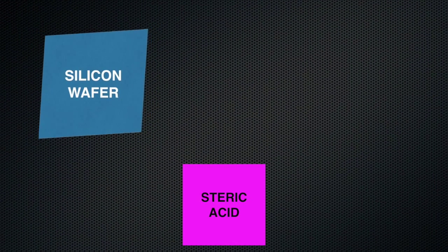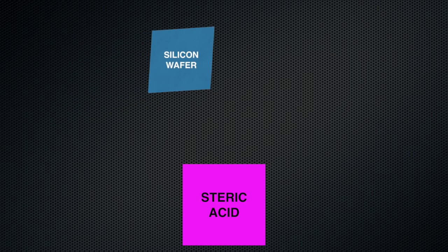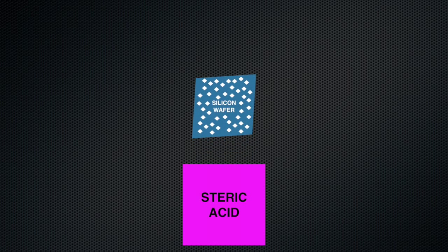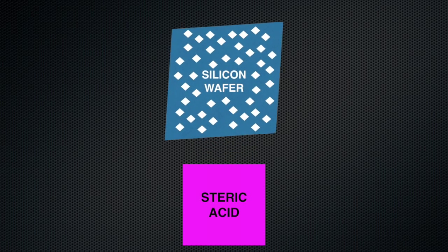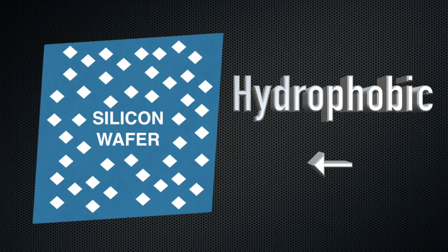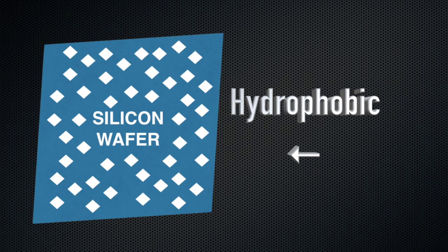Now, scientists have discovered different ways of how these lotus effects or the hydrophobicity can be manually made by humans. One of the examples I researched was a silicon wafer. It was made hydrophobic by dipping the silicon wafer into a solution of stearic acid several times, allowing the solution to crystallize on the surface of the wafer. These crystals are kind of like the bumps on the lotus leaves, and the wafer became hydrophobic, and scientists actually dripped water and it repelled water.